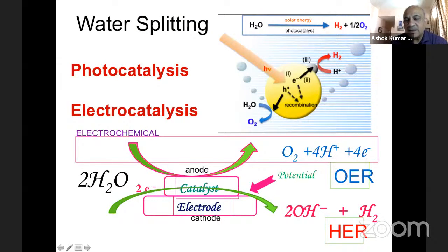So if you have a semiconductor photocatalyst, the key area is you need a semiconductor photocatalyst. That means you need a material which will absorb light, and that absorption depends on the band gap of the semiconductor. And this absorption of the solar light can be then used to generate electrons and holes. And these electrons and holes are then used to produce hydrogen and oxygen. So the issue with semiconductors is that you have to use the right band gap to absorb the right amount of photons. And the number of photons in the visible region is very high in the solar spectrum. It's 43%.